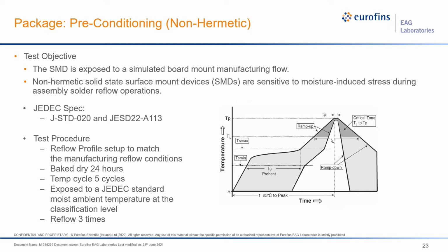After the moisture soak level, now the device goes into solder reflow to simulate the device being attached to the PCBA. The solder reflow will be repeated 3 times, and this is to simulate the device as it may go through the reflow process on top of the board, bottom of the board, repair. So the same solder reflow gets repeated 3 times.